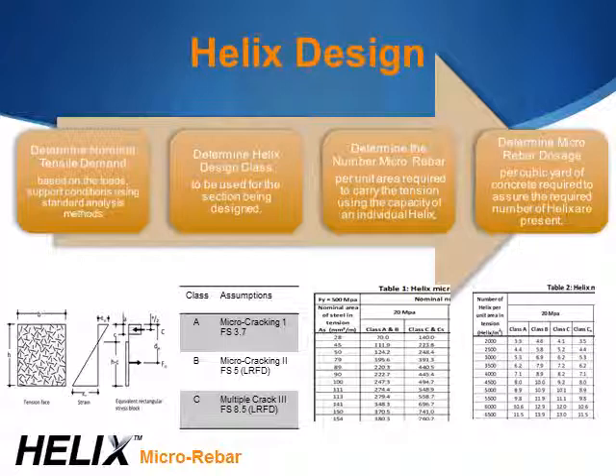So we have a class A through C system. Class A is really just slabs on grade and shrinkage reinforcement. It carries an average factor of safety of 3.7. Class B includes applications like walls and structural elements that are on ground, where the consequence of failure is higher, but still there's no danger of anything actually falling. And class C includes applications where you have something that, if it fails, it falls. And that has a factor of safety of 8.5.